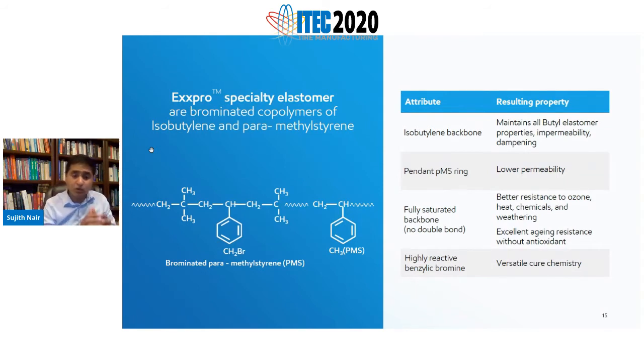Now, basically, you've got less space for the material to actually go. It's tighter, more tortuous, and so your permeability goes down. Also, the segmental mobility of this bulky group is much lower, and hence it's difficult for air molecules or oxygen molecules to pass through this. So we have seen that the permeability of Exxpro is significantly better than bromobutyl, and we'll show you some results for that as well.